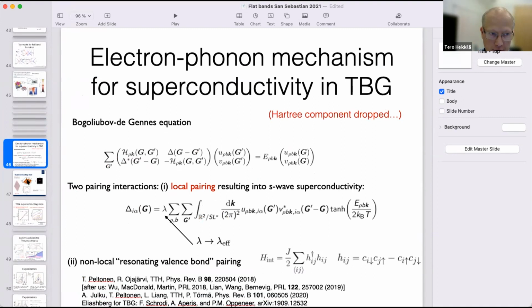The Bistritzer-MacDonald model is assuming just a single parameter of coupling between these twisted layers. But we don't use that one. We use a model where we parameterize the coupling between the atoms in terms of the distance and the direction of the coupling. We find the nearest neighbor couplings in the unit cell, and then we take the full coupling matrix.